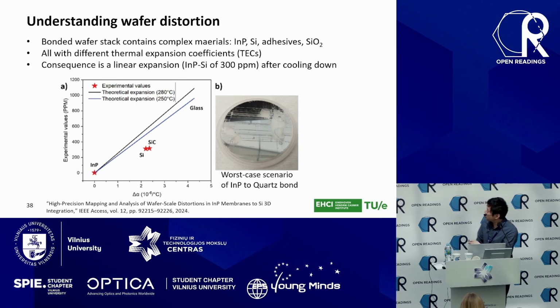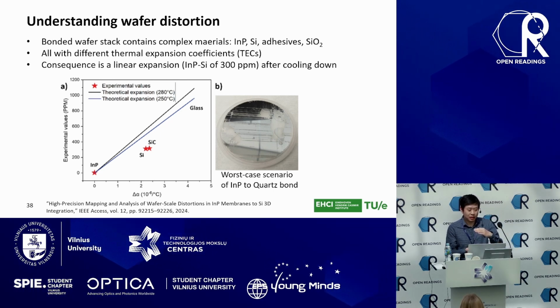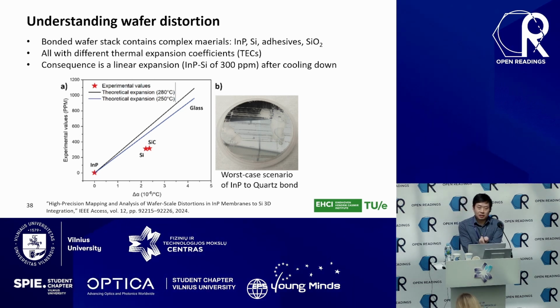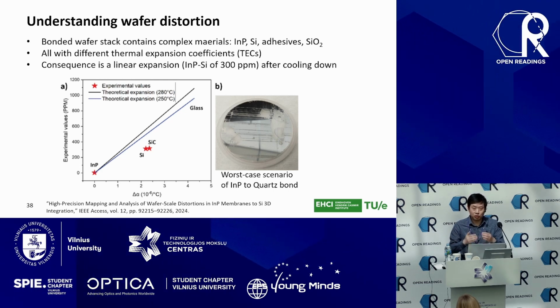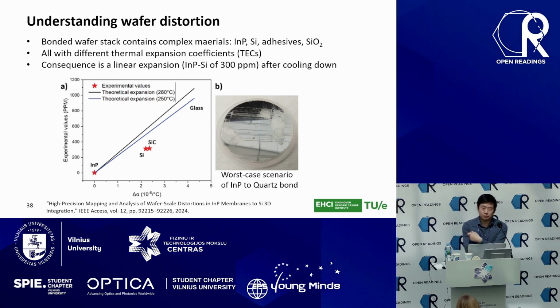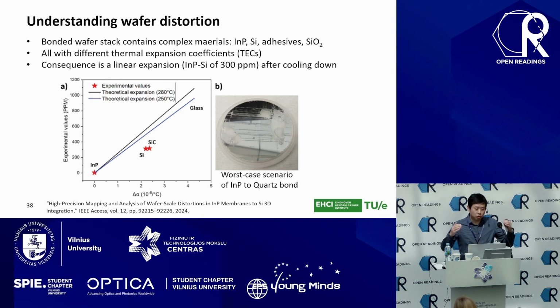I'll show you a worst case scenario when we try to bond indium phosphide onto a glass substrate, which has the highest difference in expansion coefficient. And you can see that the indium phosphide membrane, indium phosphide is fragile, right? It's so fragile that it cannot overcome the strain built inside the system, and it cracks into pieces. And of course, this is a worst case scenario. But our goal is to quantify how they shrink and how they influence our system.